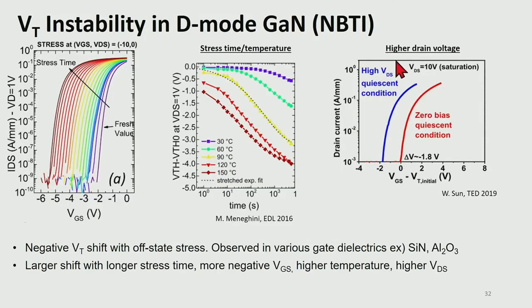So in the depletion mode device with a gate dielectric, the negative VT shift is the main concern. If you see this left figure, the fresh device shows about minus 2 volt VT. But after a negative gate voltage stress, VT becomes more negative. So the longer stress time makes the amount of the VT shift larger, and it is also accelerated by the higher temperature. And also, high drain voltage can affect this negative VT shift. If you see this right figure, after high drain voltage stress, the transfer curve is shifted from the red curve to the blue curve. So multiple factors can trigger this negative VT shift: the gate or drain voltage stress, longer stress time, and higher temperature.